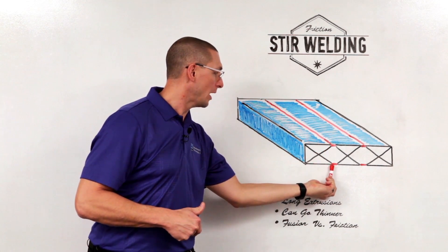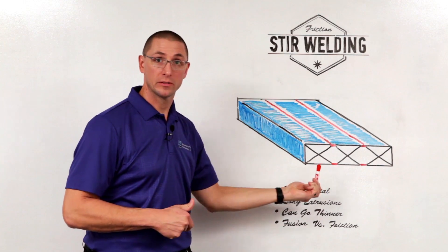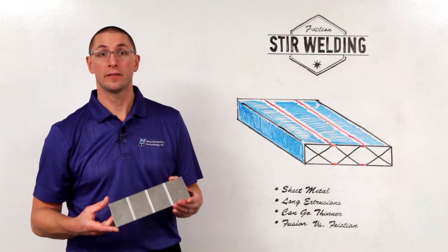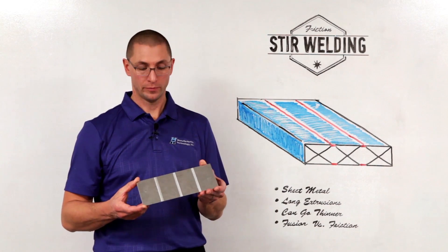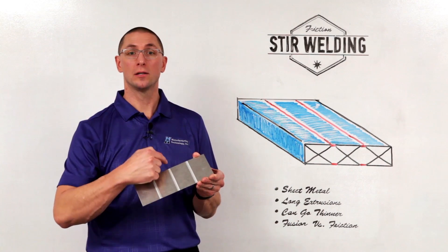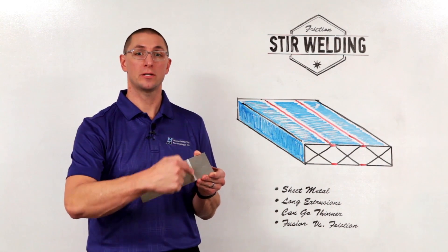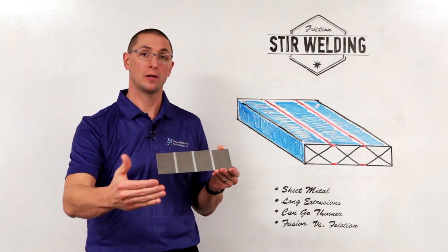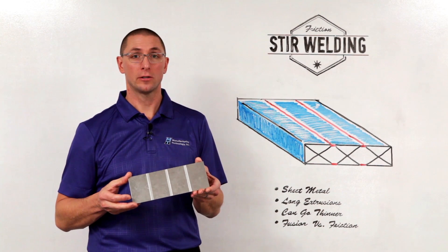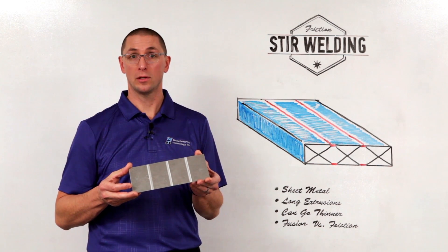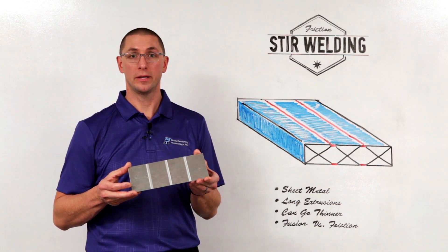You can also weld top and bottom in the case of this hollow extrusion. Friction stir welding can be used to weld very thin materials — this is four separate pieces of aluminum sheet metal welded along these three seams. These can be very wide and very long, and friction stir welding can weld materials down below one millimeter in thickness.